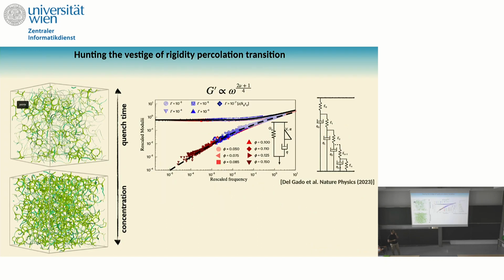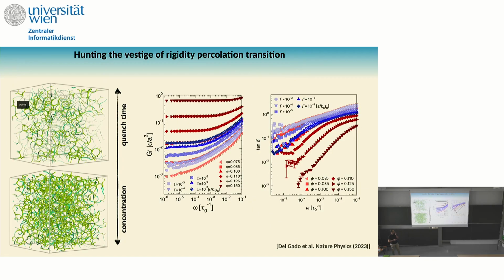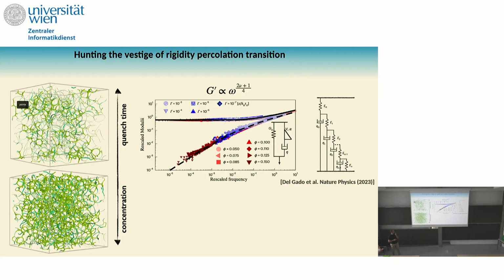The answer is yes, and the way you can do it is that you can rescale your modulus and your frequency such that all the curves that I was showing here will fall into a master curve that is given here, for G prime and G double prime. And if you try to fit this with a model, what you need is some ladder model where you put your elements in a hierarchical way, and you need an infinitely large number of elements in order to fit your system.